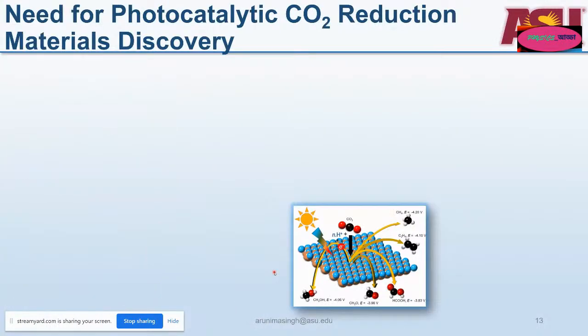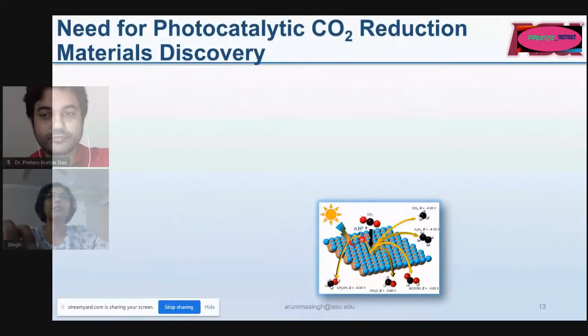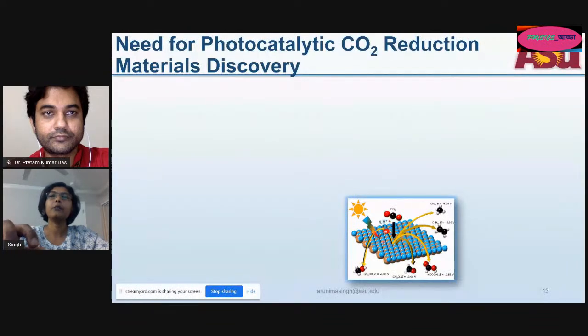What we need is suitable photocatalysts. I'm going to talk specifically about the CO2 reduction reaction, where you convert this greenhouse CO2 into usable fuels. Here in the figure at the bottom, you're looking at sunlight, which shines on a photocatalyst. If the sunlight has sufficient energy, the photocatalyst is going to generate an electron. And if you put CO2 gas in the system, bubbled along with some water which has protons, then you can facilitate these reactions where you form an alcohol, an aldehyde, formate, CH4 and C2H4, and many other products.